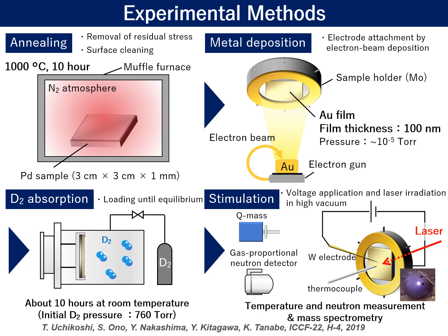Our experiment. First, we annealed a palladium plate for the purpose of surface cleaning and to obtain a complete single crystal structure for reproducibility. And then we deposited a gold thin film onto one surface of the palladium plate as an electrode for electric bias application and a diffusion barrier for deuterium. Next, we let the palladium plate absorb deuterium. Finally, we applied electric field and optical power to the deuterium-loaded palladium plate.